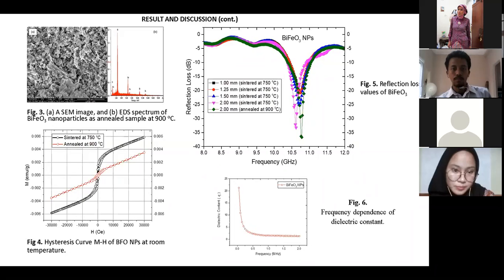Figure 6 shows the relative permittivity of BFO nanoparticles annealed at 900 degrees Celsius. It is found that the relative permittivity values decrease as frequency increases, while its dielectric constant below a frequency of 100 kHz is still higher, contributing to the increase in the reflection loss values of BFO nanoparticles in our result, because reflection loss value is directly proportional to the relative permittivity values.